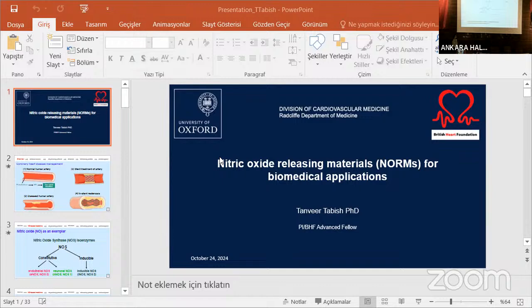So if we use this amine group, polyethylenimine, as a nucleophile, it can attack the electrophile of GSNO and it can split nitric oxide. So we use polyethylenimine on graphene oxide, and this is just the basic characterization using Raman, XRD, FTIR, and TGA to show how much polyethylenimine or polyethylene glycol has been conjugated to graphene, and it can also improve the dispersibility of graphene oxide. So I'm not going into detail for a short time.